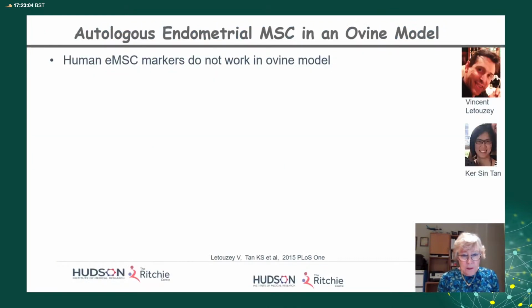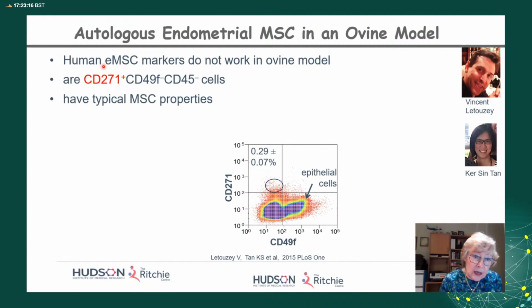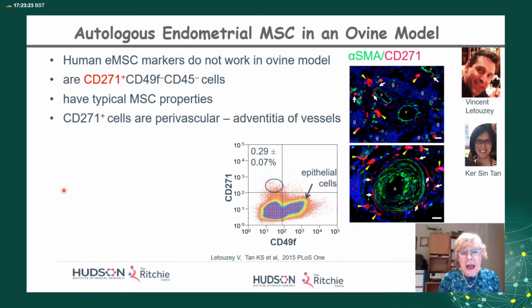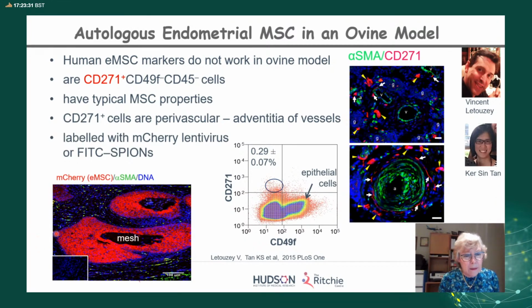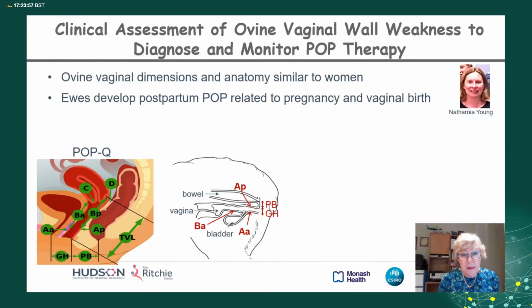Now, if we're doing an autologous model and we're using a sheep model, we need to actually get the cells out of the sheep. None of our human EMSC markers worked, but we found CD271, another MSC marker, purified the ovine EMSC, which had EMSC properties, were also perivascular around the adventitia this time in the vessels, and we could also label them. We also labeled them so that we could detect them in vivo when we implanted these cells, because they are autologous. We've used permanent marker, an mCherry lentivirus, and you can see these mCherry labelled cells here, implanted in around a mesh in a sheep vagina, and also FITC SPIONs, which are superparamagnetic iron oxide nanoparticles, which I'll show you in a minute.